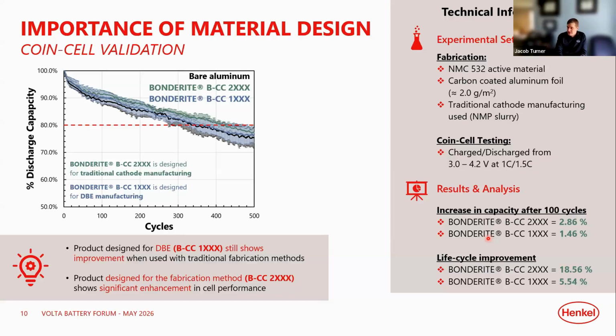If we use a material that looks the same on the foil but has different underlying properties, you do see some benefit. There is a little bit of benefit here. We do see some increase in initial capacity that furthers the life cycle improvement. But to add manufacturing steps and potential cost inside of the cell, this might not be good enough for the cell maker. So the point here is that it's not one size fits all.